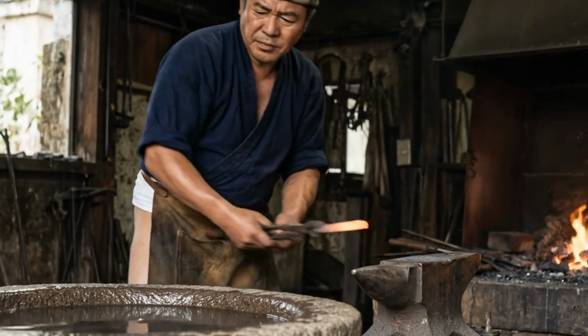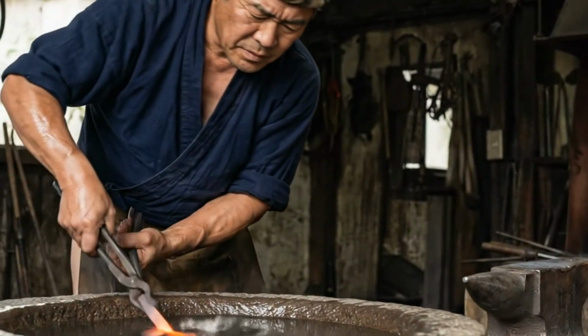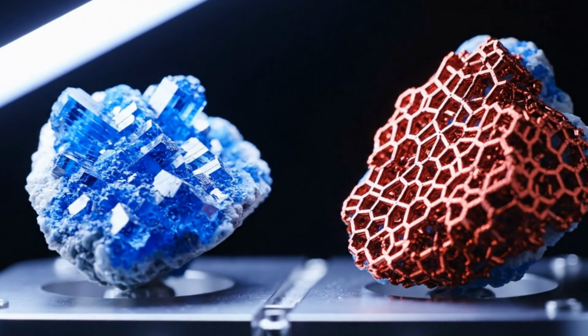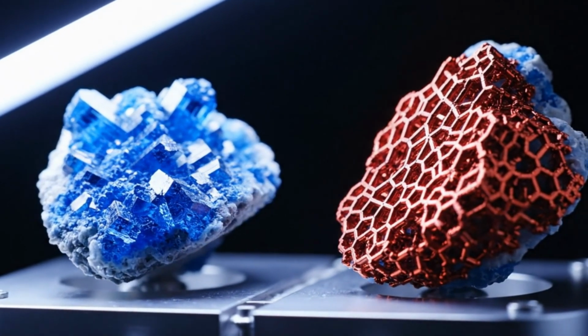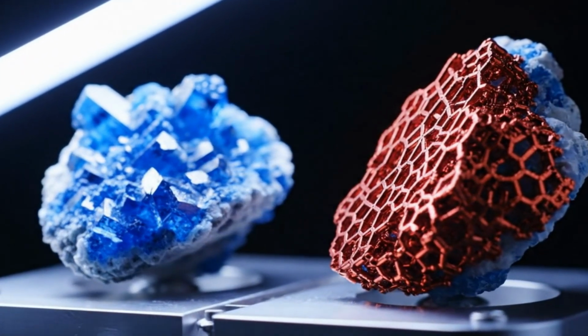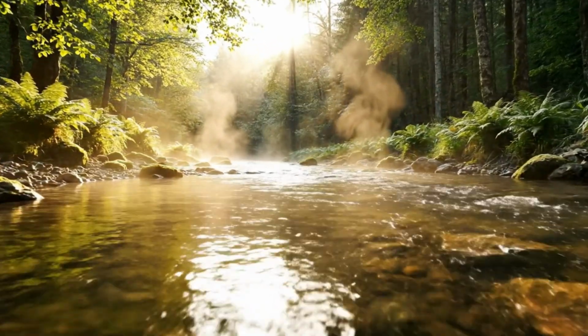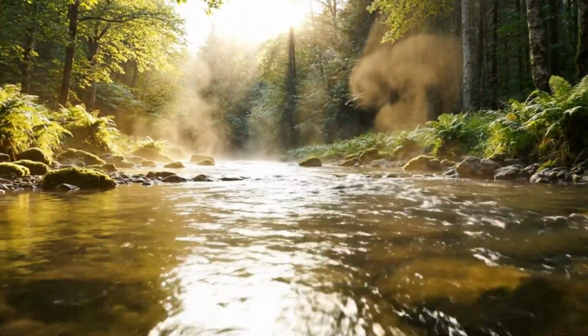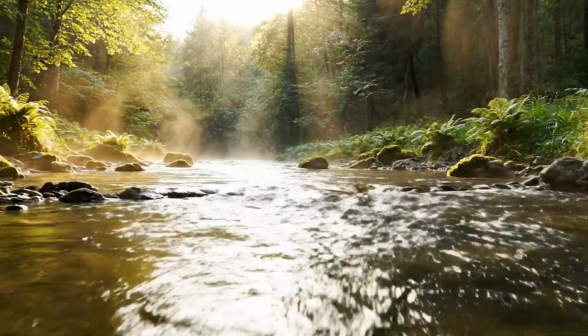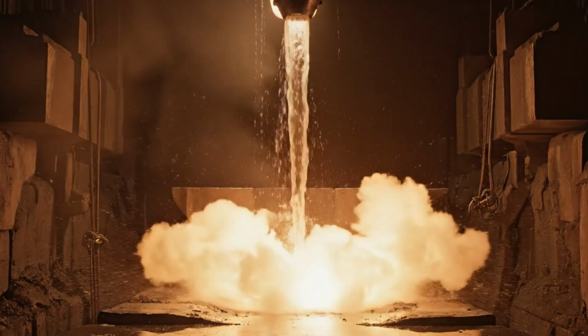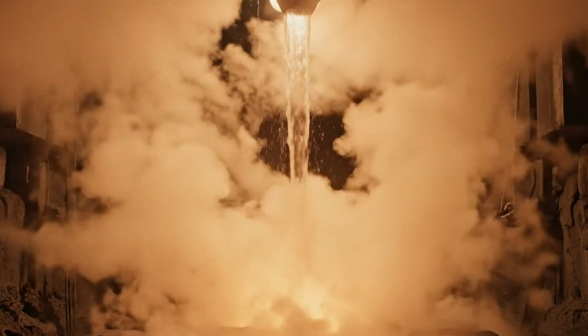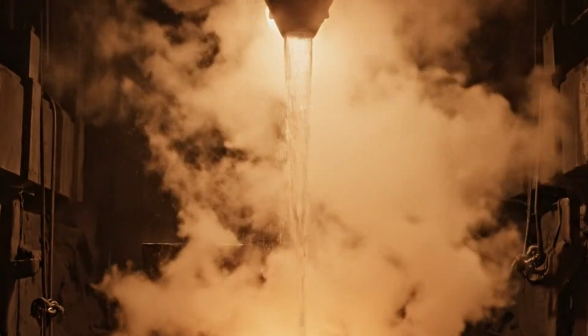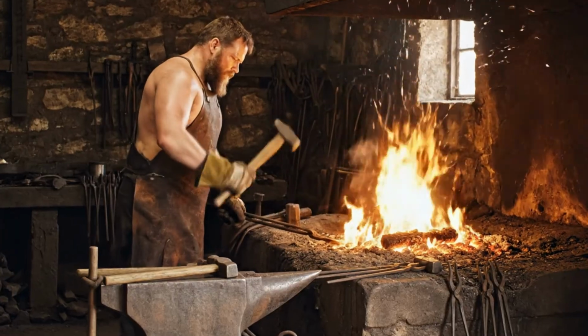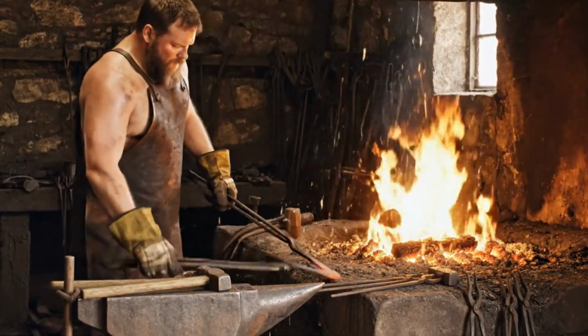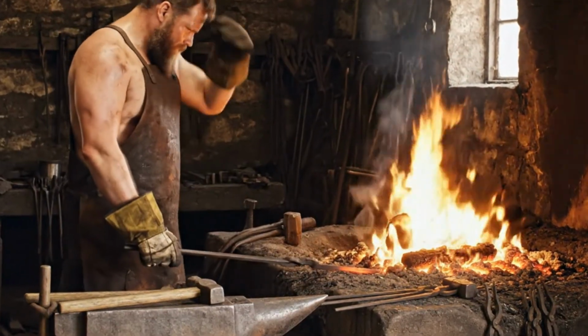One detail that often surprises people encountering this subject through a technical lens is the role of water temperature in the quenching step. The same blade quenched in cold water versus water held at a higher temperature produces different results in the crystal structure at the edge. Smiths in different traditions and different climates developed quenching protocols adjusted to local conditions, including the specific water sources available to them. The mineral content of the water, not just its temperature, influenced the result. This was discovered empirically across centuries of practice, before anyone understood the thermodynamic and crystallographic reasons for the variation. The smith knew the answer long before science knew the question.